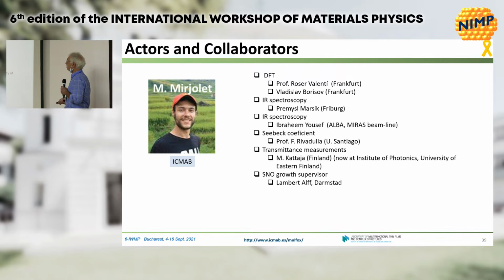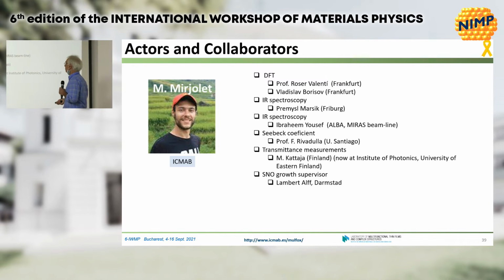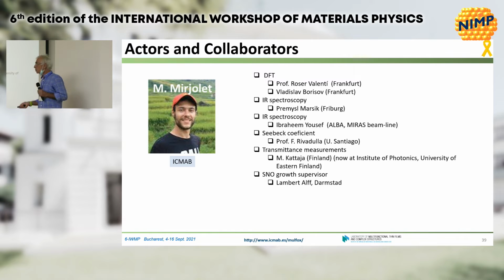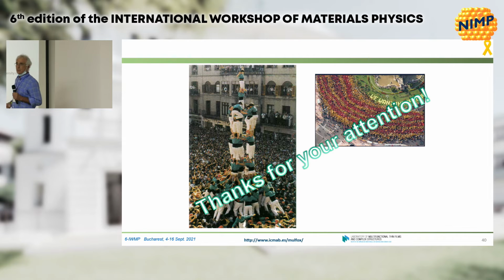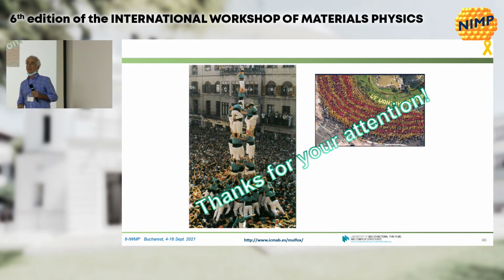Roser Valentí in Germany doing DFT calculations and demonstrating that indeed there is electron phonon coupling that so far was not identified in these materials, infrared spectroscopy to measure the plasmonic response in a couple of different laboratories, measuring the Seebeck coefficient, transmittance measurements, and some support for the growth of strontium niobate that I have not described in detail.